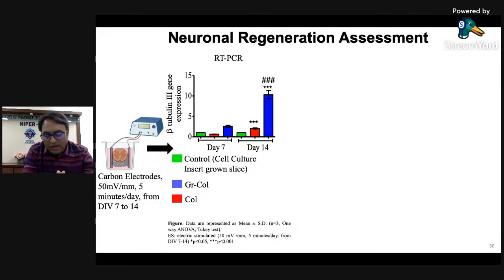We further wanted to know whether neuronal regeneration capability is there or not. For that, we grew the slice in the material and gave electric stimulation using two carbon electrodes, at 50 millivolts per millimeter for 5 minutes per day from day 7. So up to day 7, we allowed this slice culture to attach onto the material, and from day 7 to 14 we gave this electric current treatment every day for 5 minutes.